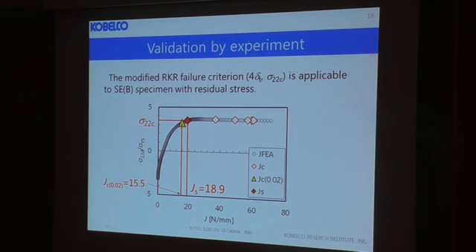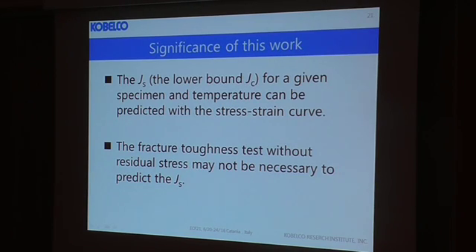Thus, it was concluded that the modified RKR failure criterion is applicable to SEB specimens with residual stress. In addition, the validity of the method for predicting JS was confirmed. The success in the current work indicates that the JS for a given specimen and temperature can be predicted with the stress-strain curve, and the fracture toughness test without a residual stress may not always be necessary to predict the JS.